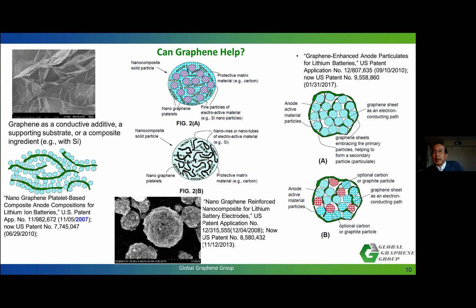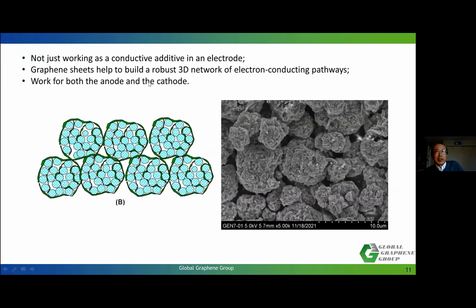Later in 2009, 2010, we used graphene as an encapsulating layer. In other words, graphene is not a conducting filler anymore. As you can see, graphene can do a much better job if you don't just use it as a conductive additive in an electrode. Graphene can help build a robust three-dimensional network of electron conducting pathways. For example, if you have graphene encapsulating all those silicon particles, then you can see this green color forming a conducting network. So as graphene scientists, we need to think beyond just using graphene as a conducting additive. I think the entire industry appears to be going in that direction right now.